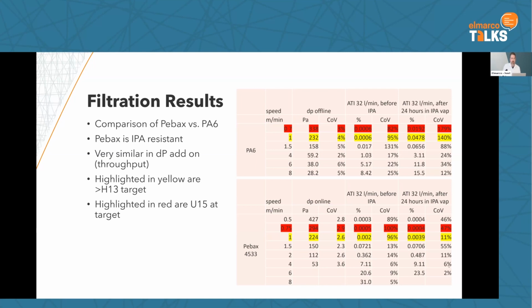And you can see the PA6 loses a little bit of filtration efficiency from IPA, but it still maintains quite a bit. You can see the Pebax does even better in terms of IPA resistance. We don't really lose the efficiency after discharging. This is quite important for us in air filtration applications.